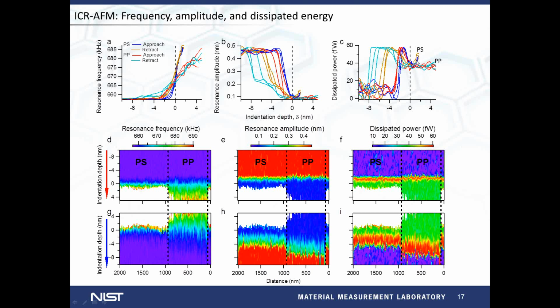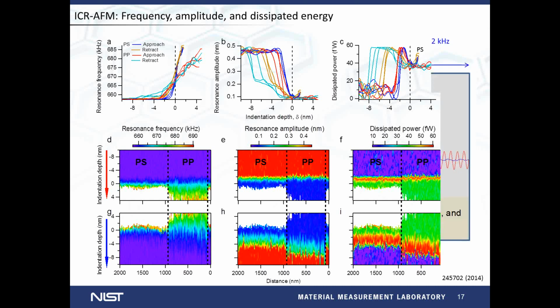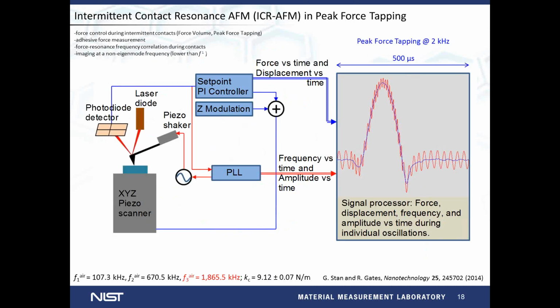It is conceivable that this is associated with the viscous response of the material, indicating that polypropylene is less viscous than polystyrene, maybe due to its semi-crystalline structure. On the retract curves, light blue and yellow, we can see a large increase in the dissipated power accompanying contact rupture over about 4 nanometers for polystyrene and about 6 nanometers on polypropylene. So the idea is that overall this analysis indicates that during one approach-retract cycle, a much larger amount of power is dissipated during contact formation and contact breaking than during contact deformation itself. Now, to switch to the last topic, one impediment in force volume, as we know, is that it is very slow.